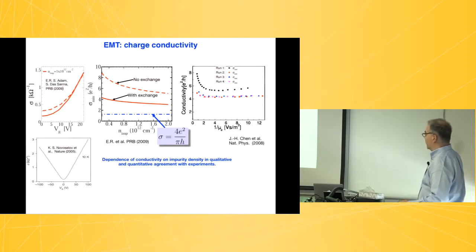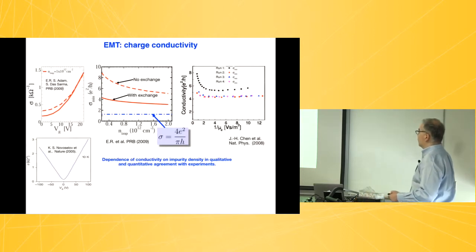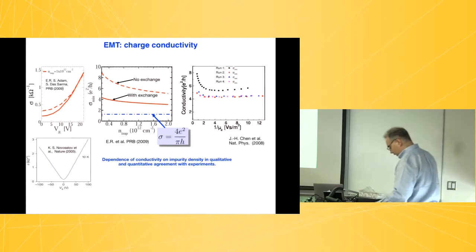These are the experiments that were obtained almost 10 years ago by Andre Geim. But more interesting, this is a comparison between our result as a function of the impurity density for the minimum conductivity with the minimum conductivity obtained by Michael Fuhrer by changing the amount of scattering centers. You can see that he also finds the interesting behavior that this does not depend much on the amount of disorder in the system, as we also find numerically.